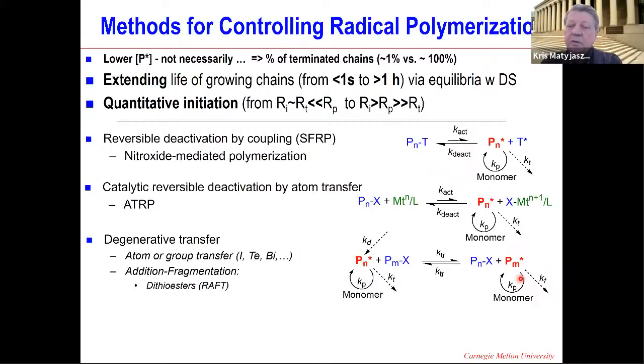So the key feature for the control in all of these systems is how many times you propagate before you exchange, how many times you propagate before you deactivate, either in ATRP or these nitroxide-mediated systems. If you add one to two monomer units, you get polymers with very low dispersity. If you propagate 1,000 times, you get conventional radical polymerization.